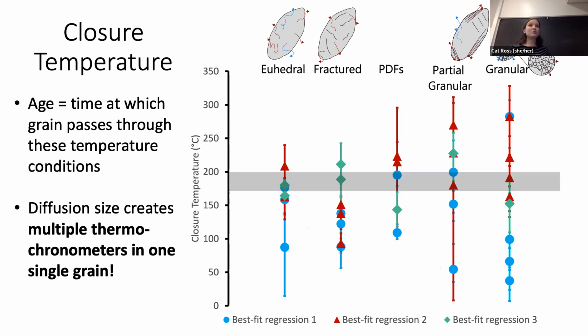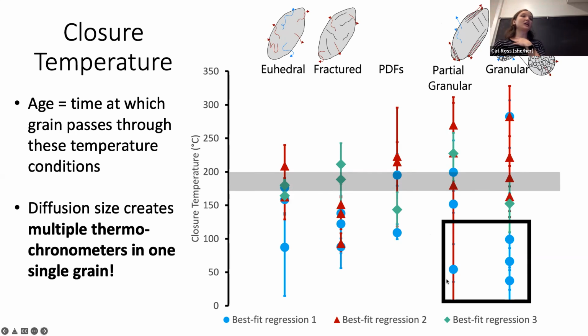And then finally, we can look at the closure temperature, which is what we're sort of interested in for habitability. This is the temperature at which this grain is passing through at a certain age. So if we get an age of a crystal, that would be the temperature that we're recording here. So basically what I'd like for y'all to take away is that if we look at these highly shocked grains, we have closure temperatures that are less than 100 degrees Celsius. And this is quite cool because we can use these smaller domains to record ages of less hot material.